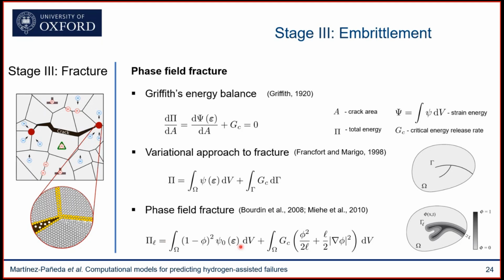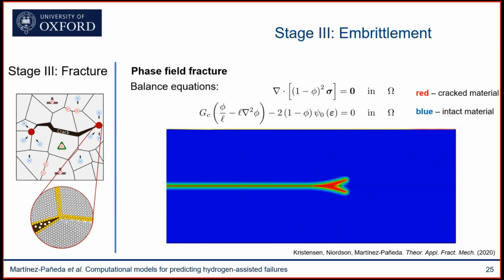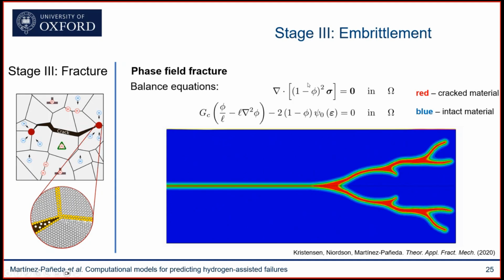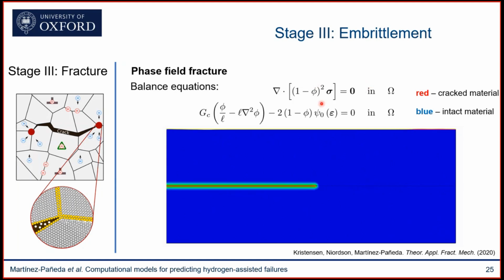And a little like a damage model, it reduces the stiffness of the metal. You can get a good overview by looking at the governing equations here. So you have a balance equation for the standard balance of linear momentum, where you will have the phase field degrading the load carrying capacity of the material.